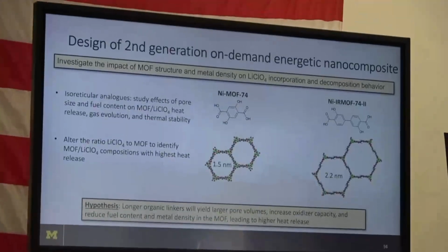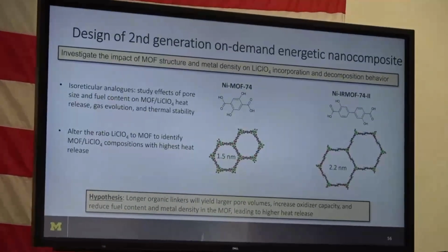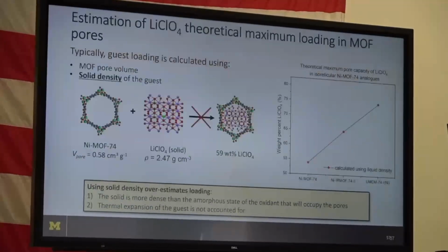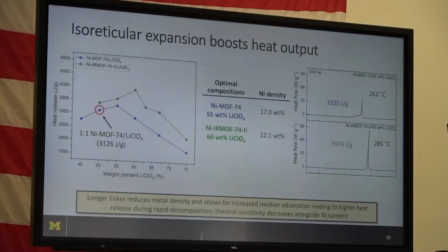and then see how that's going to affect their properties. And I think I'm going to just skip ahead to show you the effect, because I think I probably only have about 10 minutes. Is that right? Yeah. Okay, so here is when we take different weight percentages of lithium perchlorate and we mix them with that MOF, and then we look at the heat release by DSC.